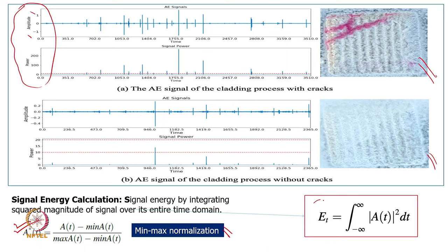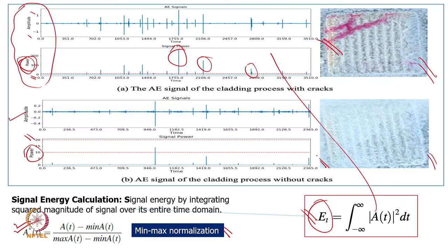And then to calculate the energy level, even though both are related, if you look at this, this is amplitude related and this is energy related, the integration from minus infinity to plus infinity. Energy and power are the same in this case. So here we are giving a maximum limit of 20, while in this case you can look at 0 to 200 plus, and we are getting a response at different places. This is with a crack and this is without crack, and they are able to differentiate based on this. Without a crack, you can see the energy level is roughly reaching 12, while in this case it can reach more than 200 also.